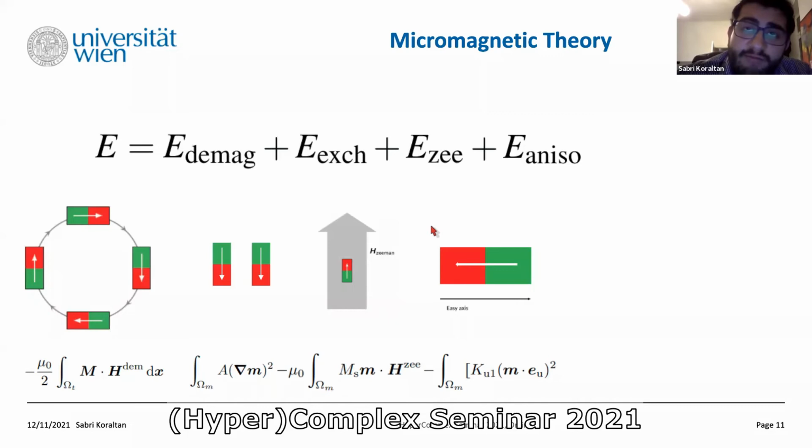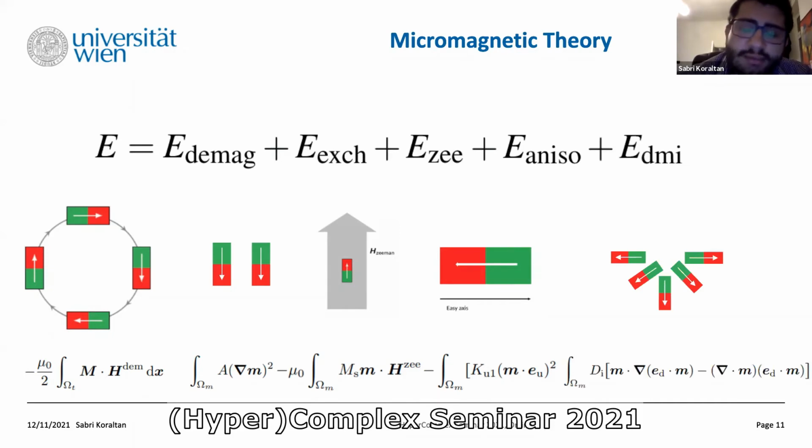But we have a perpendicular magnetic anisotropy, which means that the ground state would be a polarized state with the magnetization pointing out of the plane. But we can also include the so-called asymmetric exchange interaction, introduced in the form of the Dzyaloshinskii-Moriya interaction, which, as we discussed, rather favors a Néel wall.